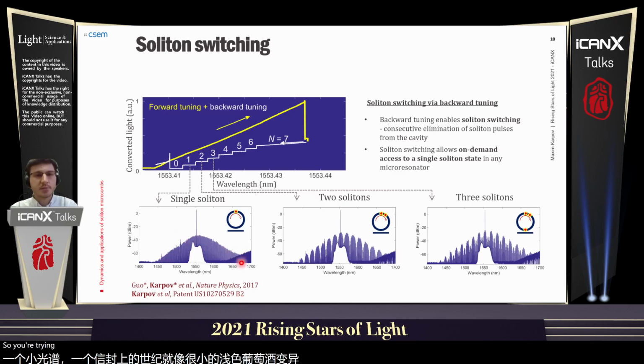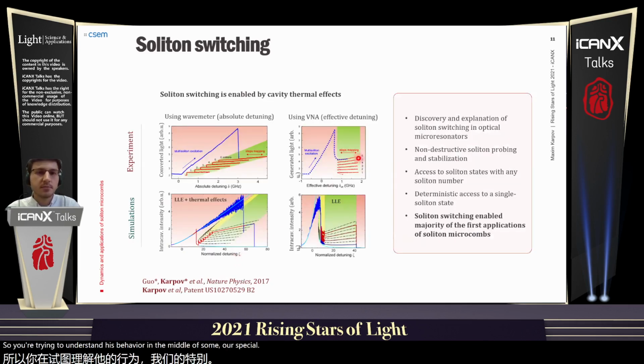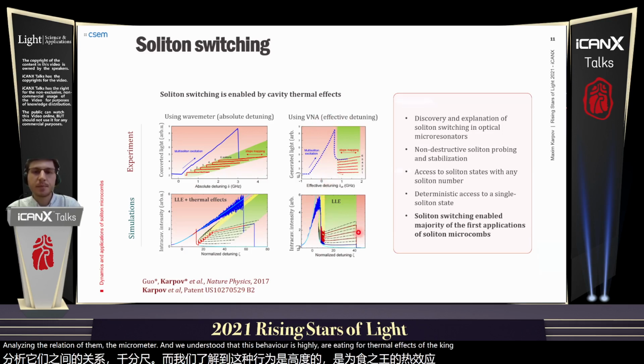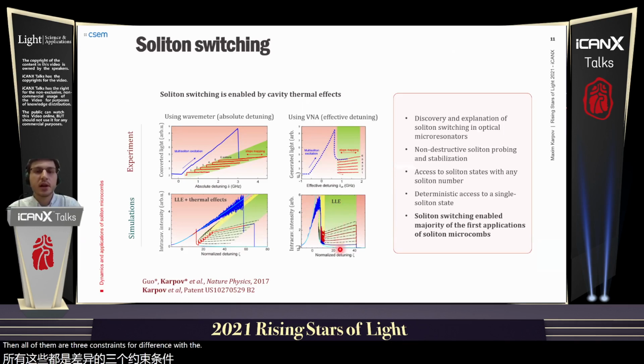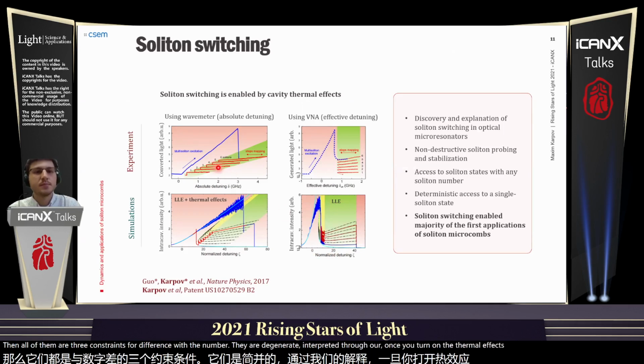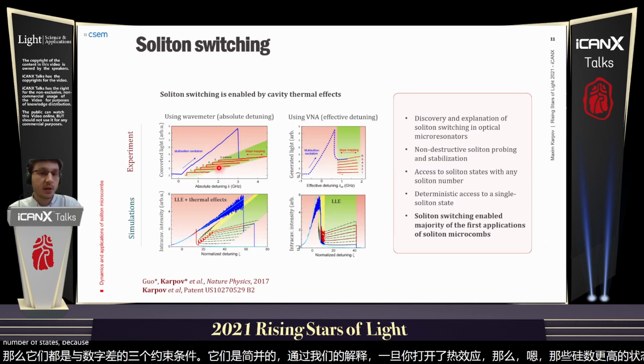So we tried to understand this behavior, and we developed some special tuning techniques based on network analyzer modulation of the microresonator. And we understood that this behavior is highly linked to the thermal effects of the cavity. If you imagine crossing the thermal effects out of the cavity, then all the soliton states for different soliton numbers are degenerate in terms of the tuning. However, once you turn on the thermal effects, the states with higher soliton numbers start to move with respect to lower soliton number states because of the thermal shift.